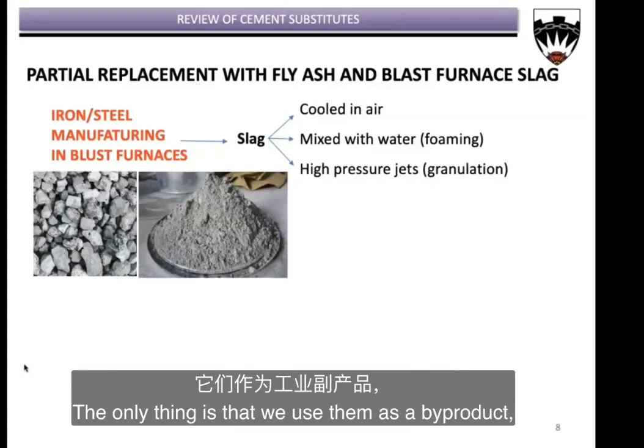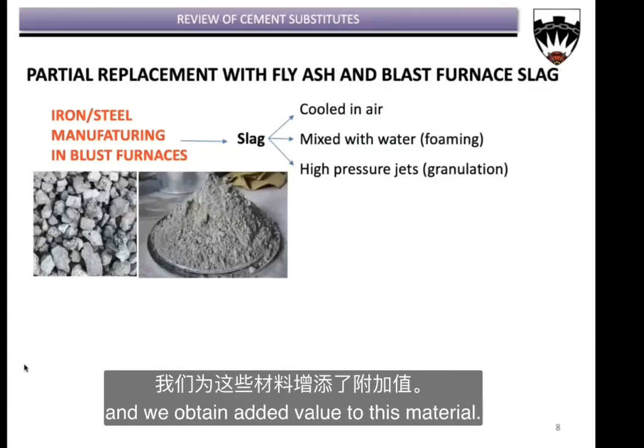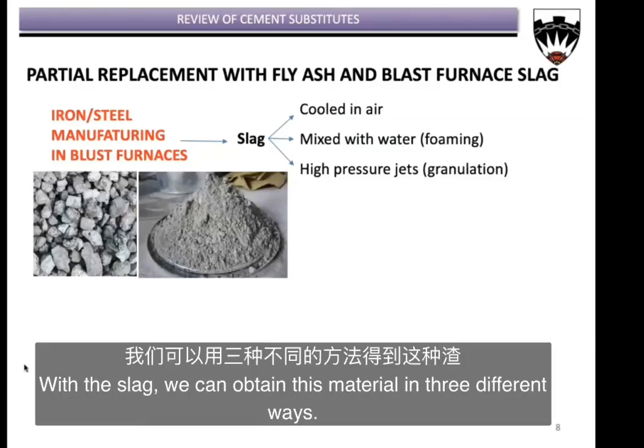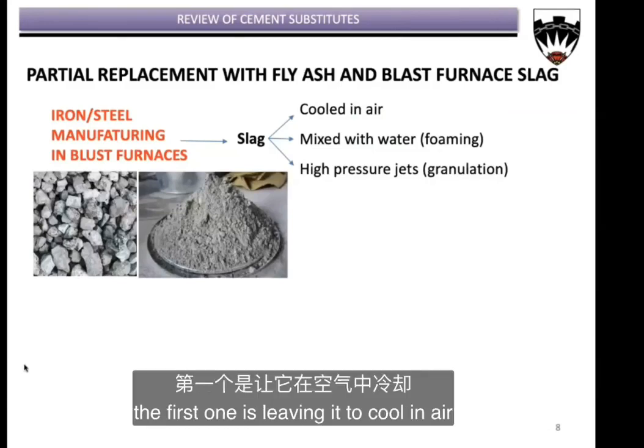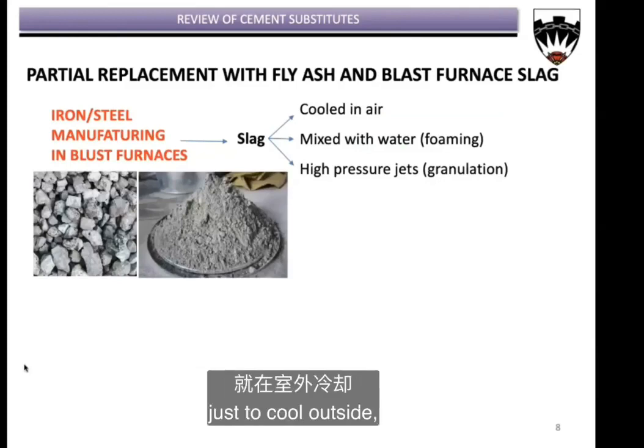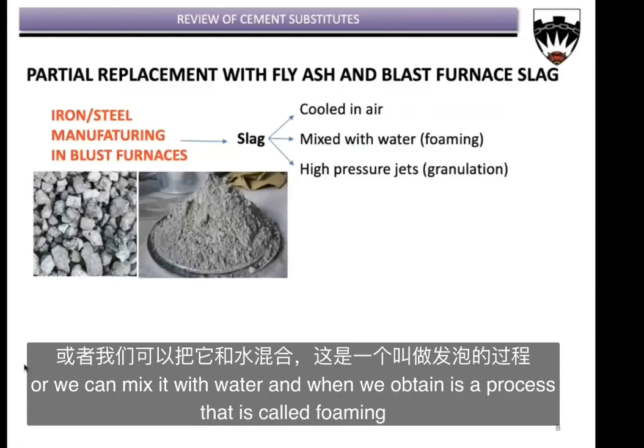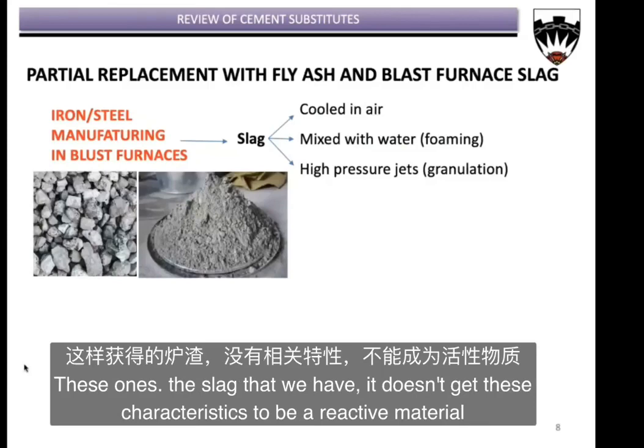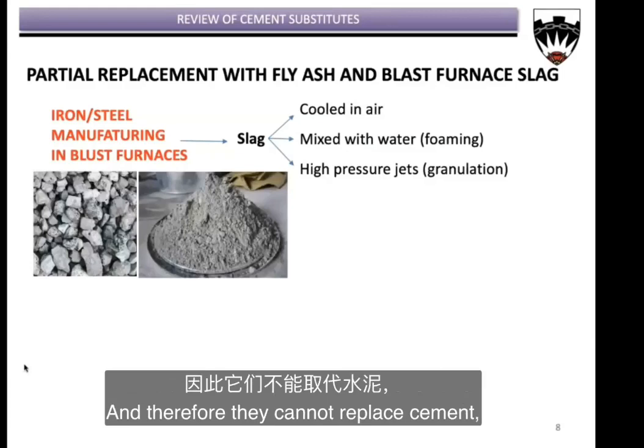The only thing is that we use them as a byproduct and we obtain an added value for this material. With slag, we can obtain this material in three different ways. The first one is leaving it to cool in air, right? So just to cool outside, or we can mix it with water, and what we obtain is a process that is called foaming, right? In these two, this slag doesn't get the characteristics to be a reactive material, and therefore it cannot replace cement.